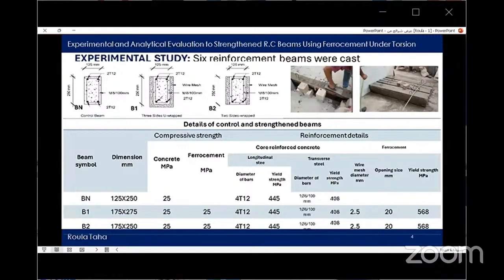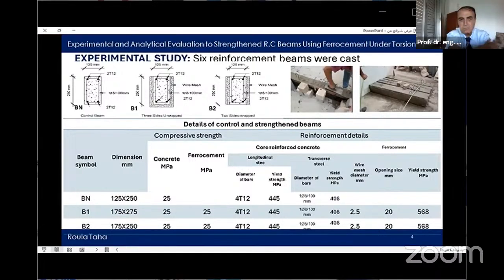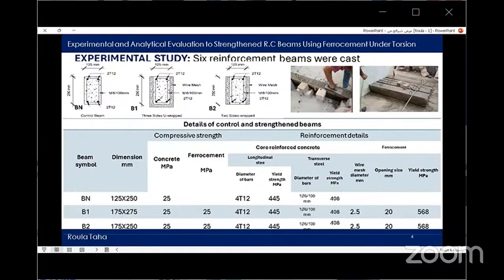6 beams with cross-section 125 by 250 millimeters were cast. All beams were reinforced with 2 bars of 12 millimeter at the tension side and 2 bars of 12 millimeter at the compression side, with yield stress 445 megapascal. Also, beams were provided with stirrups of normal mild steel, 8 millimeter diameter and 100 millimeter spacing, with yield stress 408 megapascal. To achieve the required mechanical properties, many tests were conducted. The tested beams were divided into groups. Each group had 2 beams.